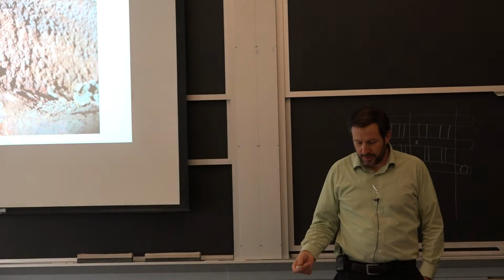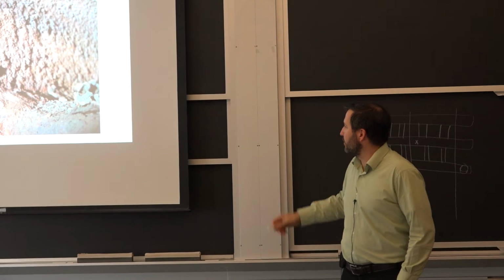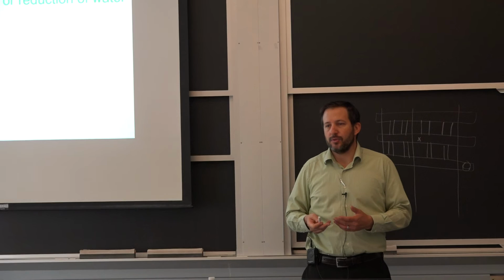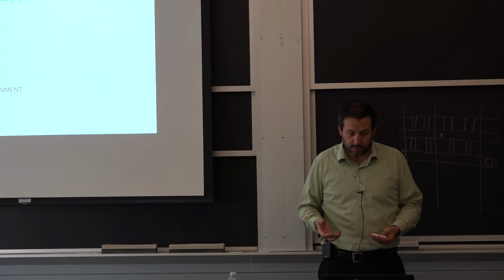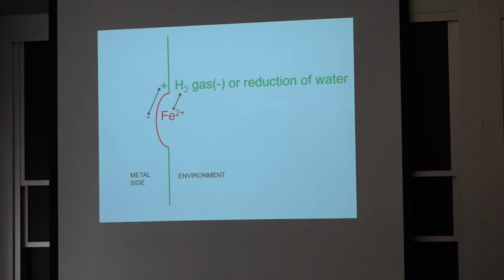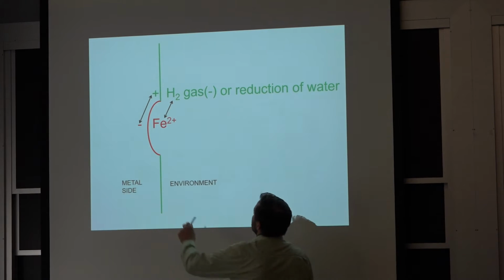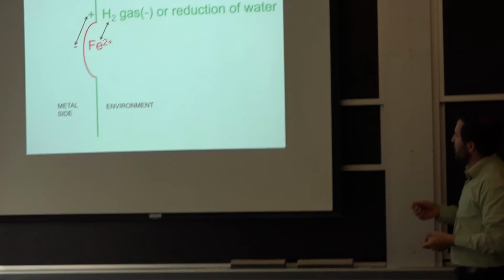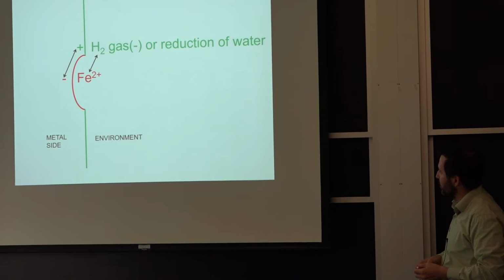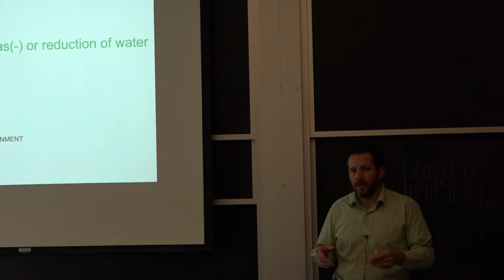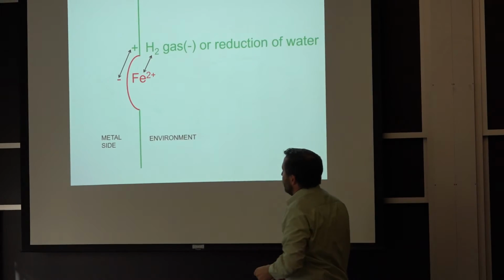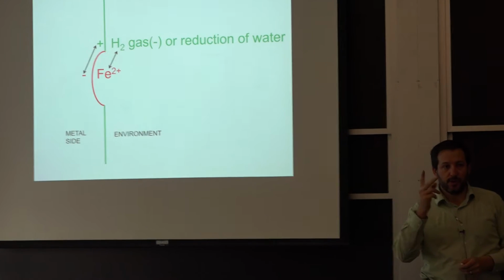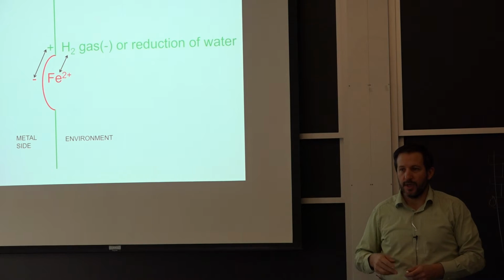Again, it's just the same material over the entire sheet, and it's rough. The reason is you always end up having anodes and cathodes, even if we call it uniform corrosion. By the time you form a reaction and you start removing material right here, what happens is you have the flow of electrons opposing that, and you generate hydrogen, or you have reduction of water, depending on your environment. After a while, you have a certain buildup where over at the cathode, the environment has changed, and then normally it will want to flip right over. So what used to be the anode and the cathode is going to completely change, and you have the reverse reaction, but it doesn't happen perfectly.